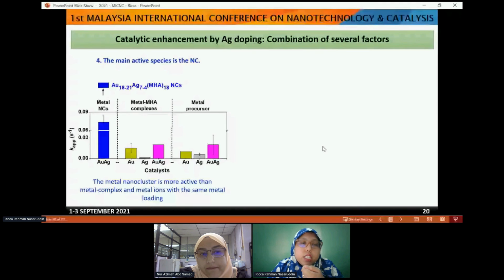And the fourth reason is, we try to identify whether it is really the cluster that is the main active species during the catalytic reaction. So we compared the performance of this metal nanocluster with the metal MHA complex. We did not reduce this mixture. We just added the metal precursor and the ligands with the same amount, and we did not add sodium borohydride, so we just have the metal ligand complex. Then we checked the activity of the mixture of metal precursor. What we realized is that the activity of the metal nanocluster is far higher. So it means that the main active species is actually the nanocluster, not the complex, not the metal precursor.